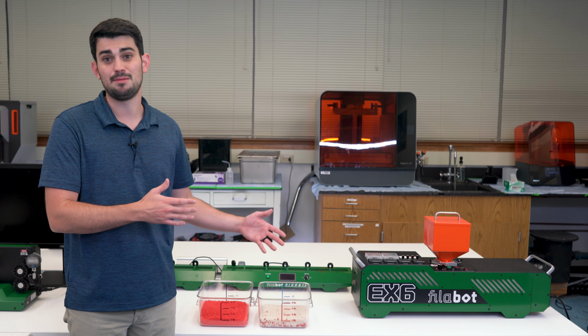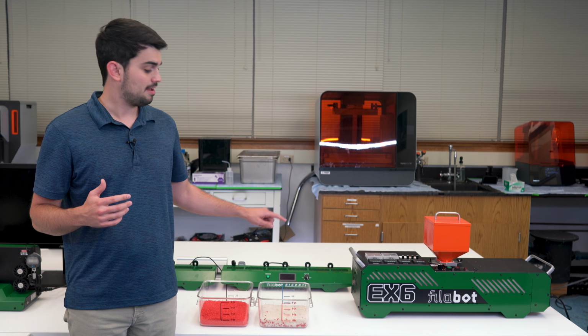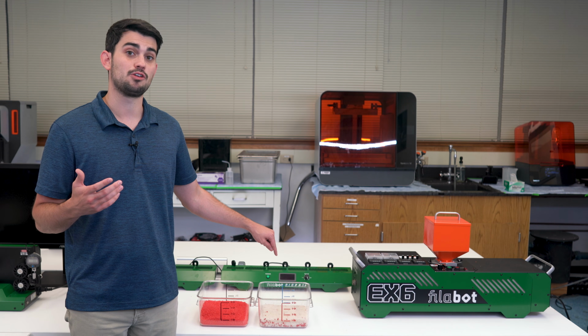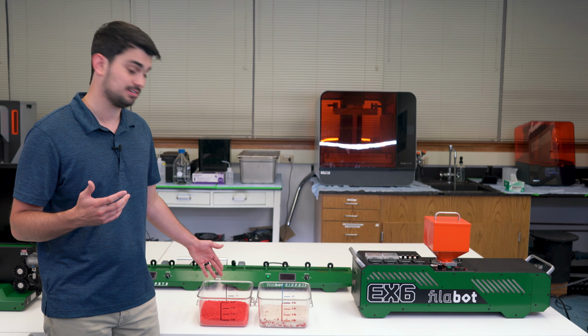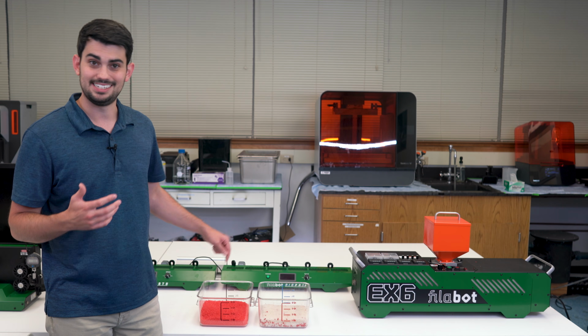However, due to how time-consuming the recycling process is, and my makerspace's high consumption of filament, I use closer to 25% reused pellets simply because I cannot produce enough recycled material. But for this example spool, I'm going to use a 50-50 blend. For the fresh pellets, I need to add half of the normal amount of colorant because the recycled pellets are already colored red. Mix these together, shake them up, and then put them in the hopper.